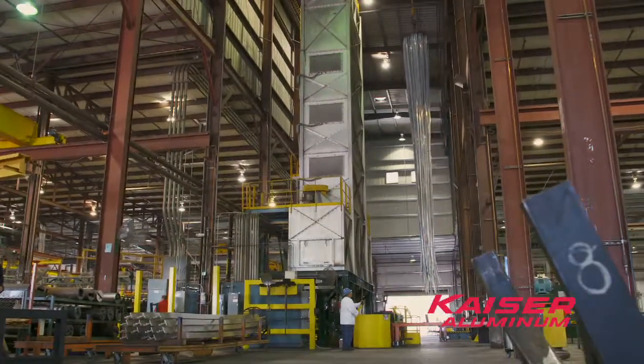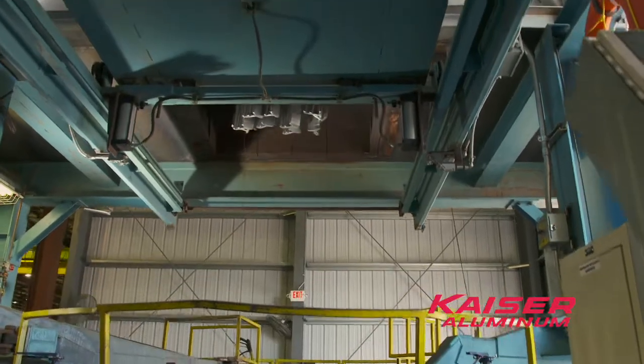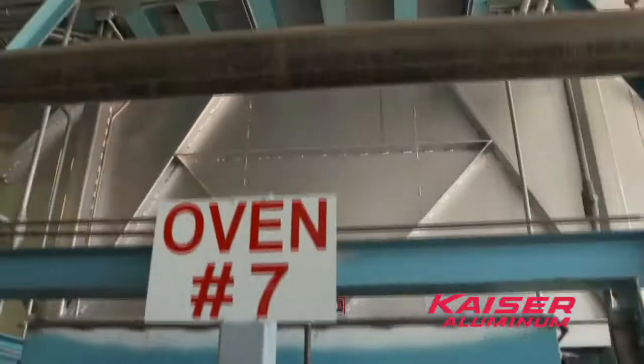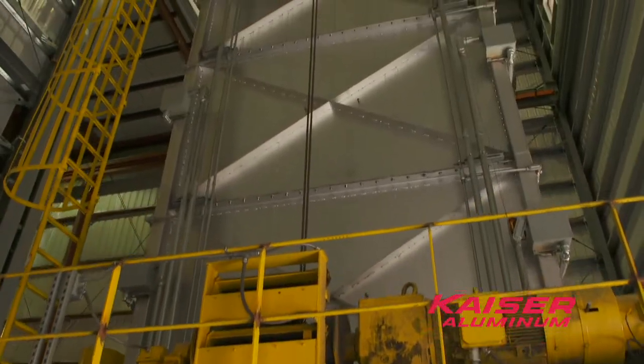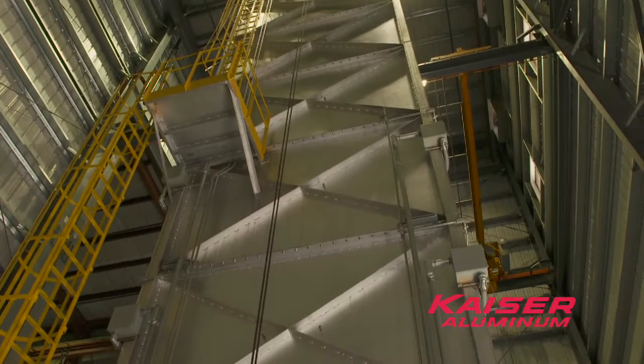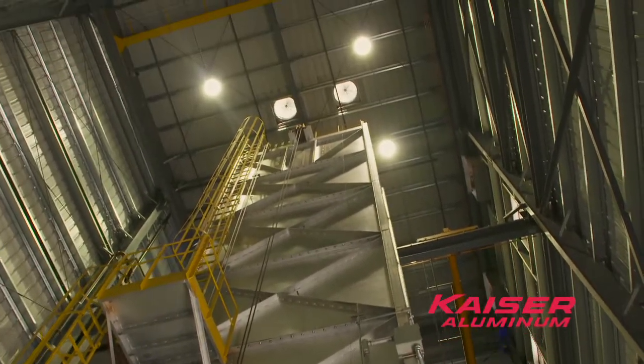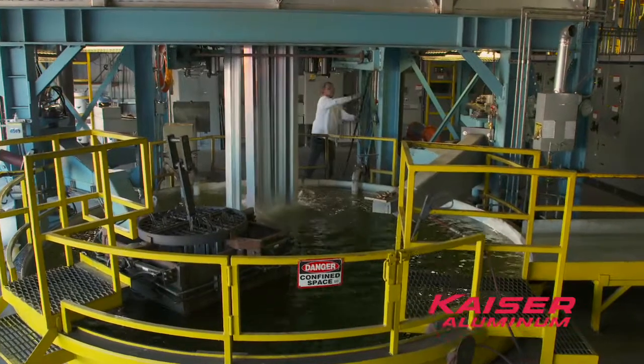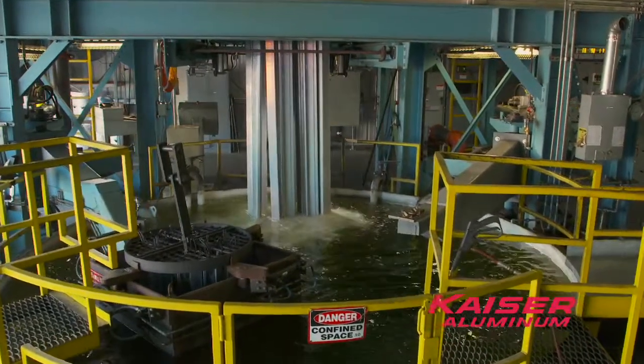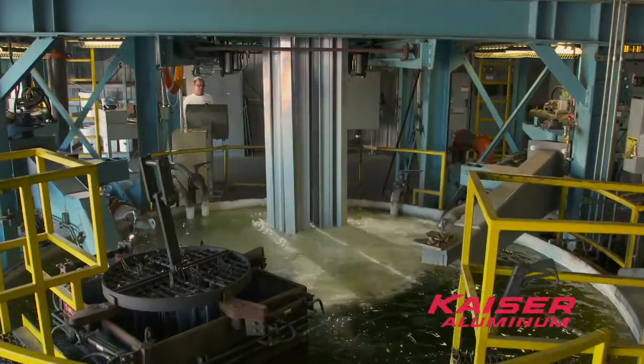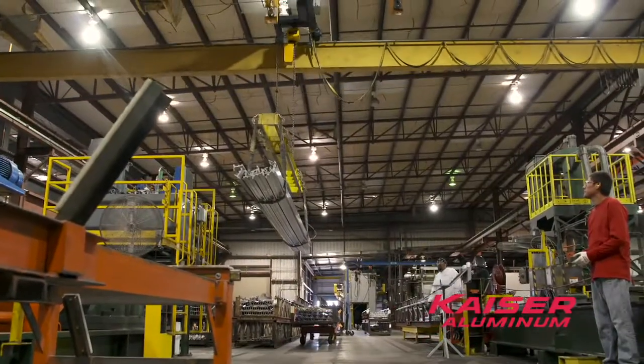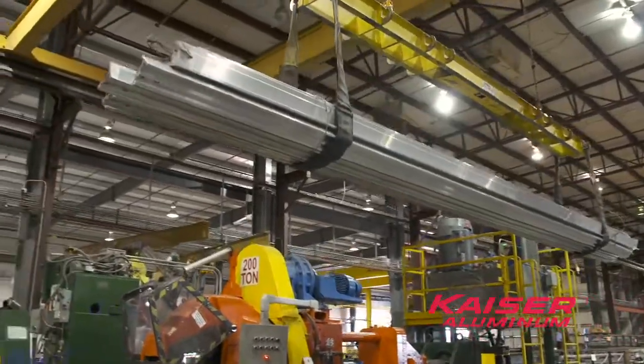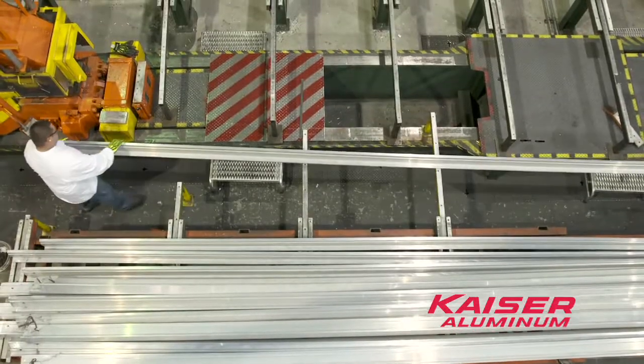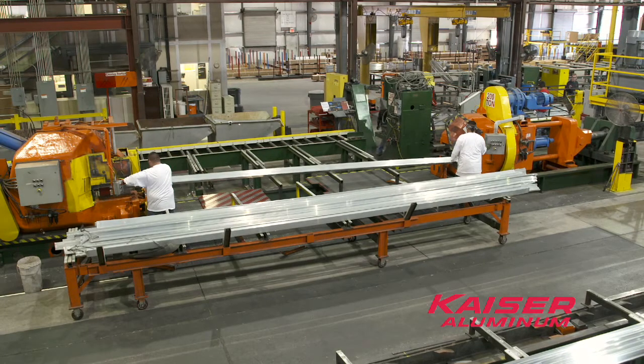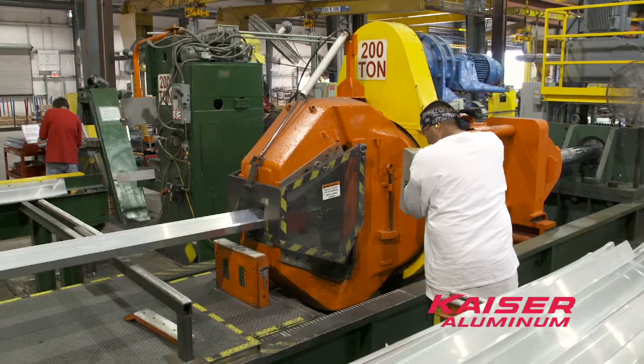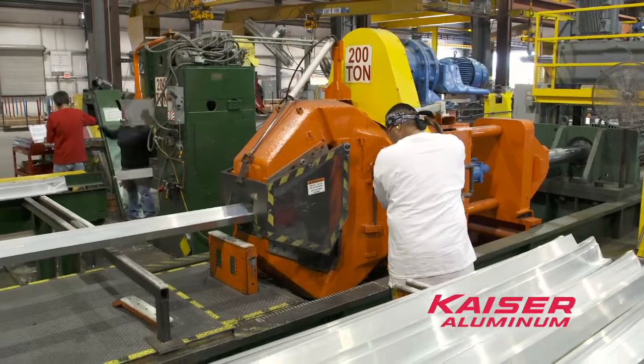After the extrusions leave the press, they're bundled and lifted into the vertical heat treat furnace and heated to a precise temperature for a predetermined time to transform the alloying elements to the desired metallurgical structure. Then, the extrusions are lowered into a water glycol solution that rapidly cools the aluminum and locks the metallurgical structure in place. Heat treating and rapid cooling can cause a buildup of residual stresses in the extrusions, which are relieved by stretching the extrusion beyond its yield point. This process not only aligns the stresses, it makes the extrusion stronger.